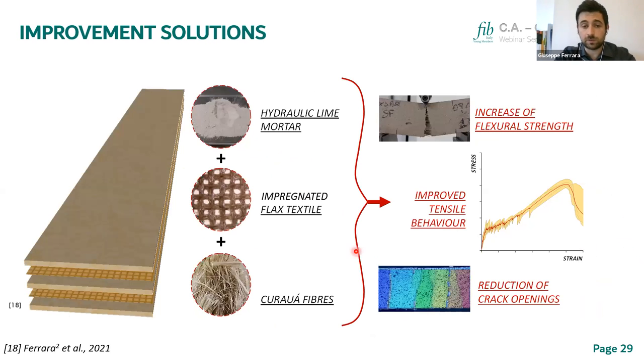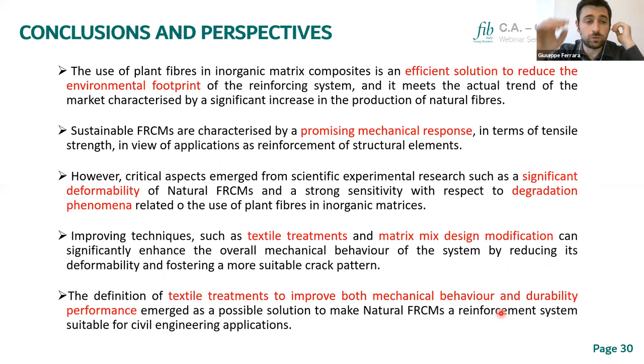So basically we have shown that by means of impregnation of plant fibers, of course, we can have an overall improvement of the tensile response of the system by increasing the flexural strength and reducing the crack openings with a denser crack pattern. So to conclude, the use of plant fibers in inorganic matrix composites is an efficient solution to reduce the environmental footprint of the reinforcing system, and it fully meets the actual trend of the market, characterized by a significant increase in the production of natural fibers and, in general, natural, sustainable resources.